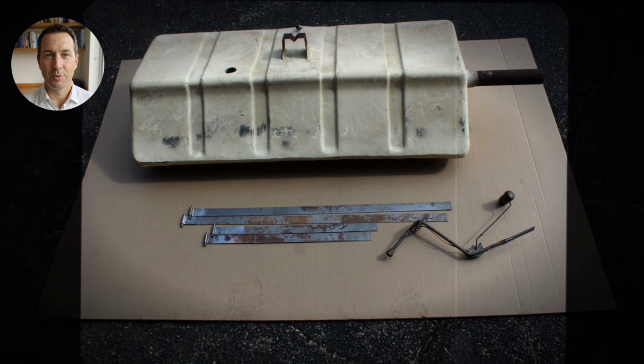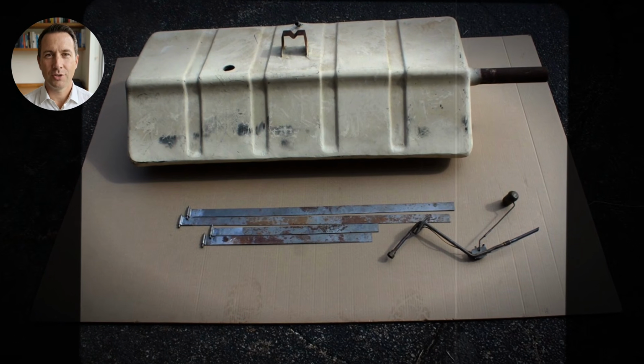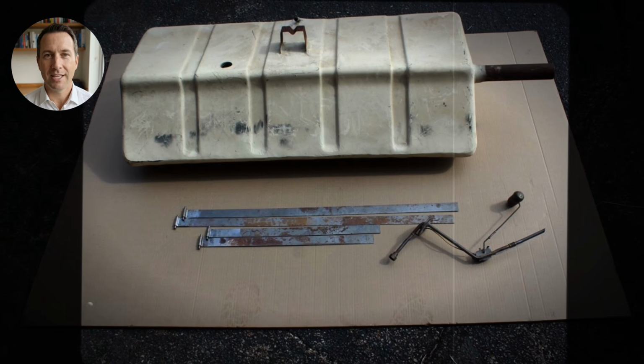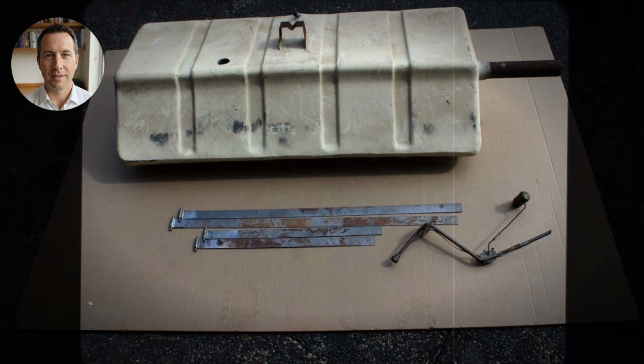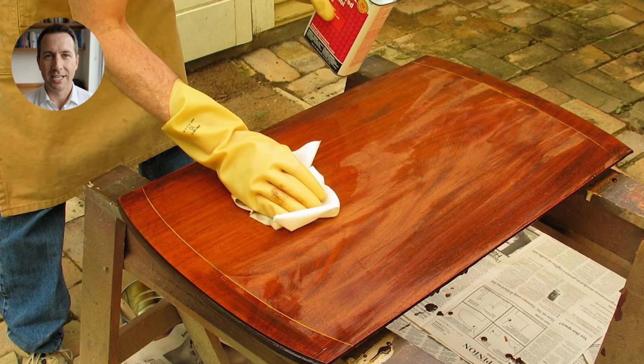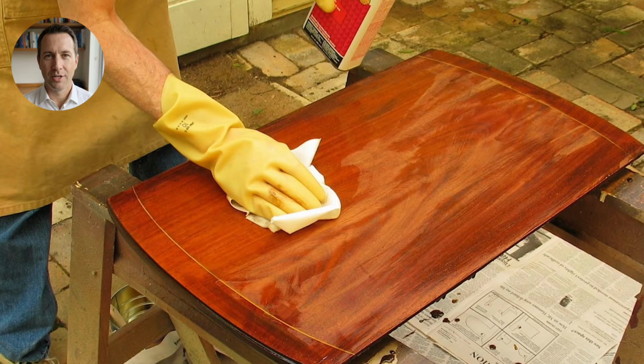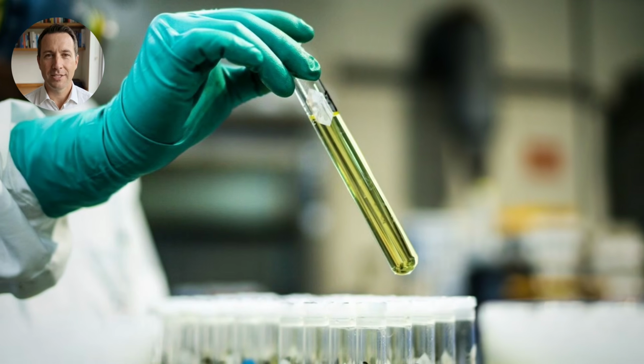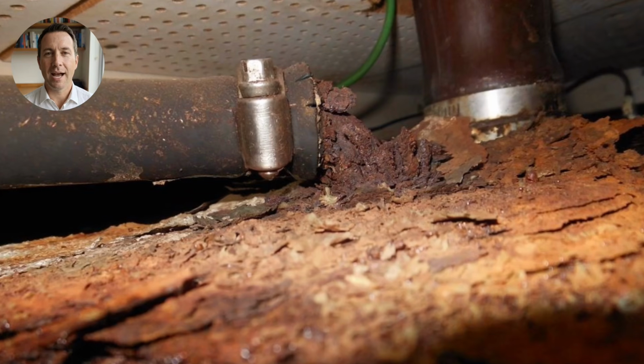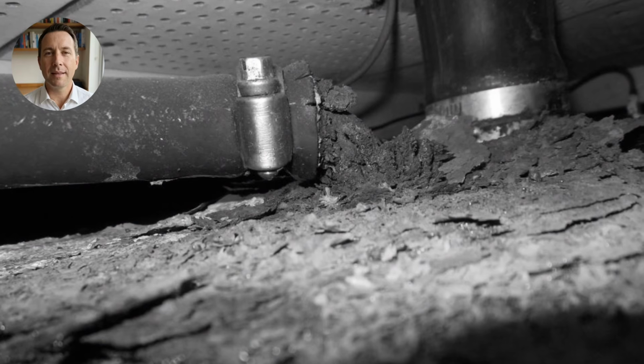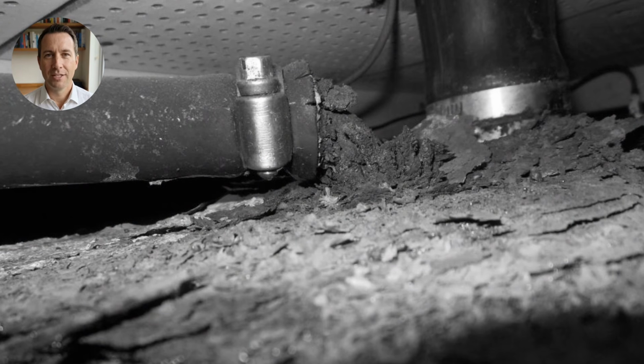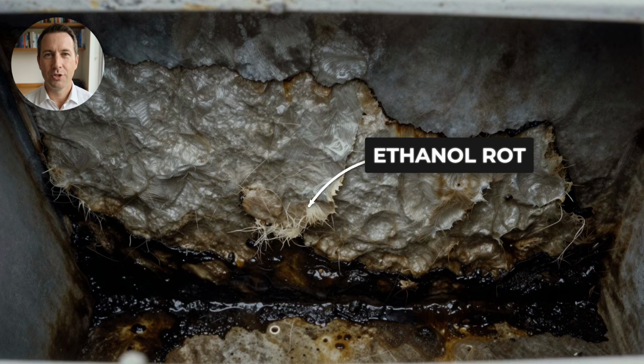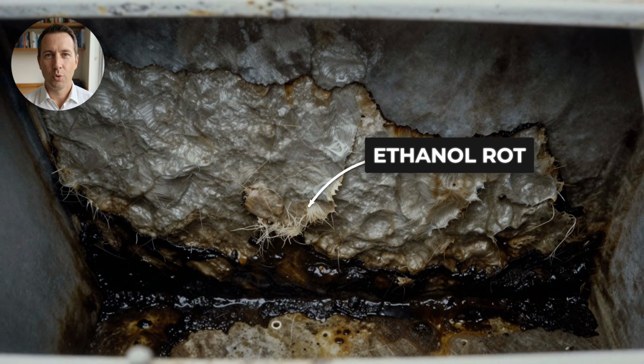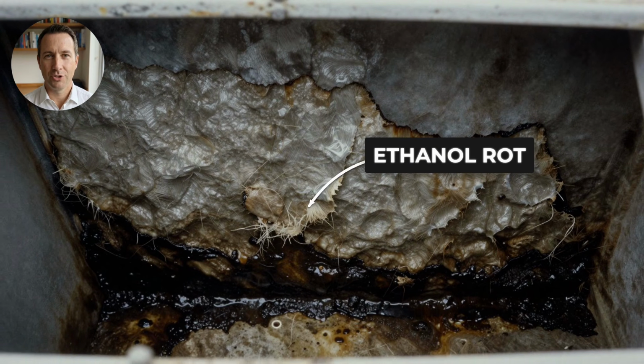Fiberglass fuel tanks built before the mid-1980s used orthophthalic polyester resin as their binding agent. Ethanol is a solvent. It dissolves that resin the same way paint thinner dissolves varnish. BoatUS laboratory testing identified di-isooctyl phthalate as the primary compound being extracted from these tanks, and the physical evidence is ugly. Cut open a degraded fiberglass tank and the inner walls look like someone took a wire brush to them.